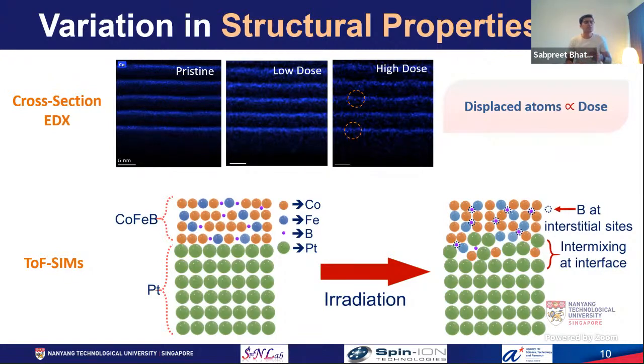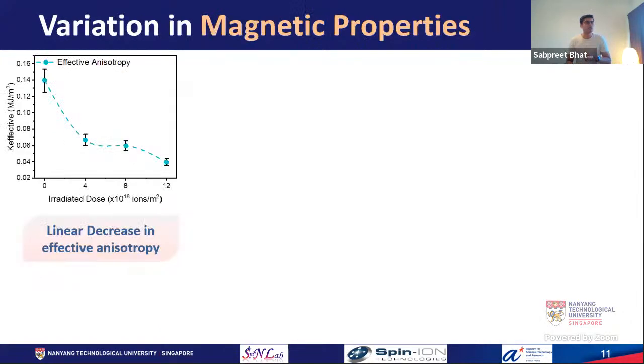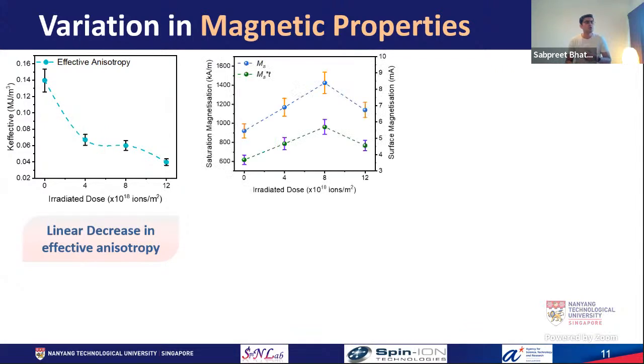To experimentally realize the effect of this, we have done hysteresis curve studies, starting with the effective anisotropy energy. As can be seen, with increase of the irradiation dose, which we restricted to 12 times 10 raised to power 16 ions per square meter to prevent the degradation of the ferromagnetic layer, the effective anisotropy is reducing, which can be understood because of the disordering of the interface. Moreover, the saturation magnetization is also increasing, which shows a higher value at 8x.